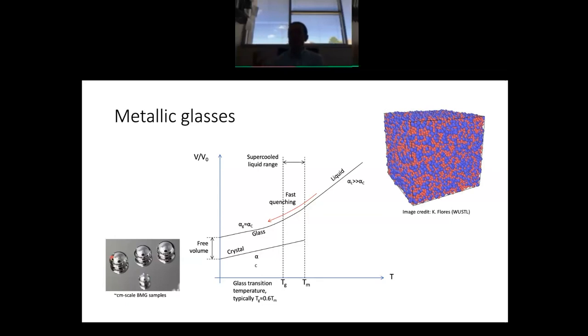And on the atomic level, these glassy materials are not crystalline. They're disordered, right? So this is an example of a simulation. Comes from the group of Catherine Flores at Washington University in St. Louis. And as you can see, no long-range crystalline order, right? So no long-range crystalline order, that means no vacancies and no interstitials, right? This is not a crystal, so it doesn't really have point defects in the usual sense. So how does it respond to radiation?